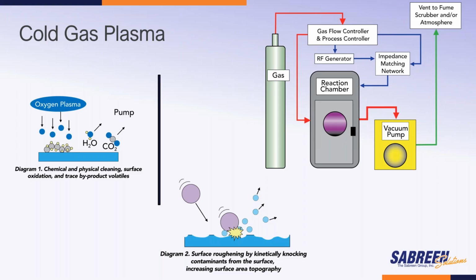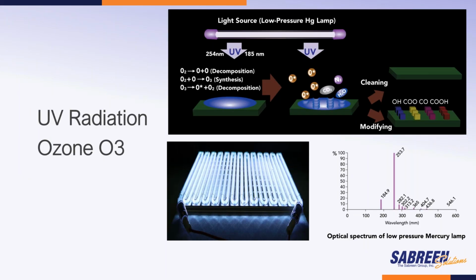And of course, most people are familiar with cold gas plasma treatment. Typically 100% oxygen is used, as well as other gases, argon and so forth, and they can be mixed in whatever proportion you want. Cold gas plasma probably is the most effective process at cleaning the surface, but it also is the most expensive, and cost matters. But the more expensive the equipment is, you're probably going to find that they have the best pumps and mass flow controls, which are absolutely critical to controlling the process.